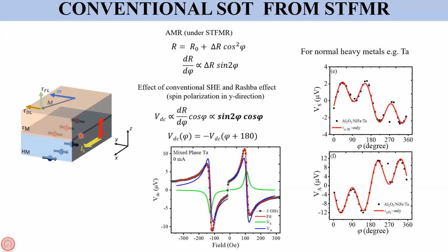If you do a detailed angular dependence, for example, this is for tantalum, you see this nice sin 2phi cos phi dependence, both for the symmetric as well as the antisymmetric component. Here, the signs of the symmetric and antisymmetric components are opposite because the spin Hall angle of tantalum is negative. This is an example from our lab only.